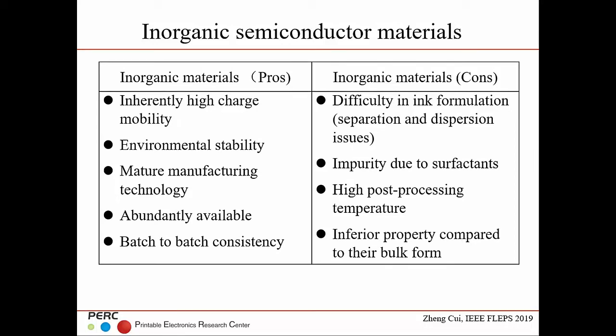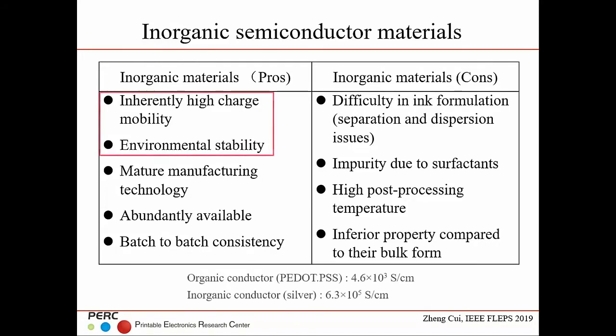So by the sintering process, you can turn the ink into solid, but the property is no longer the same as its bulk material. But the main advantage is the inherent high charge mobility and environmental stability. That's the opposite of the organic semiconductor. For example, comparing the organic conductor PEDOT:PSS and the inorganic silver, they have a 100 times difference in conductivity. So that's the reason that we prefer the inorganic semiconductor.